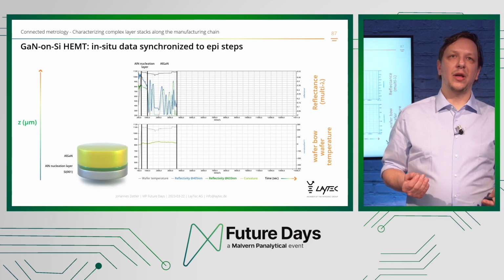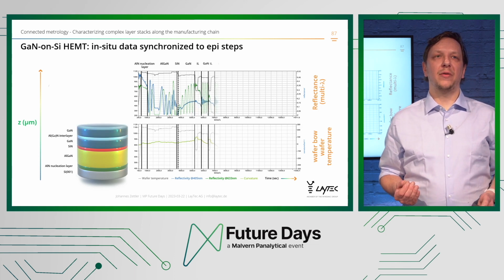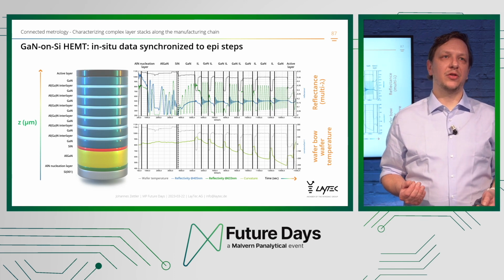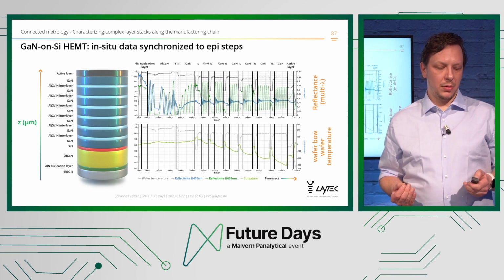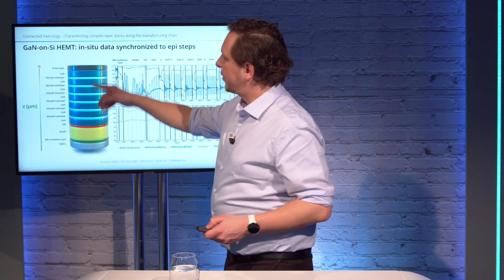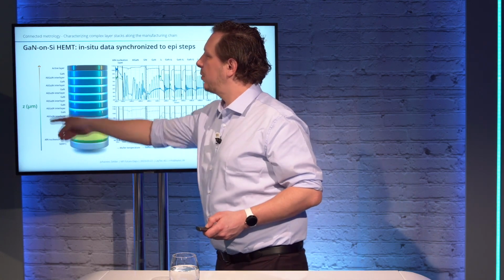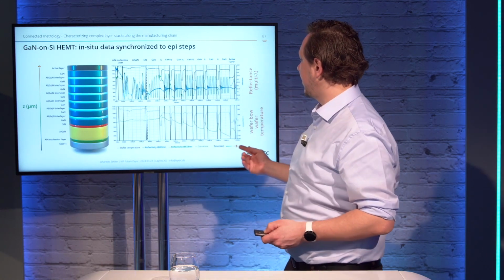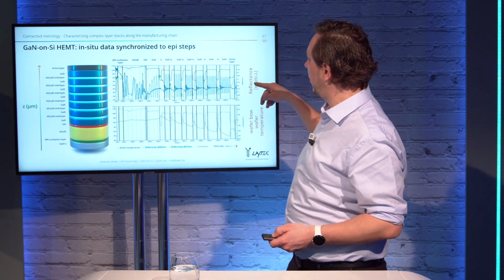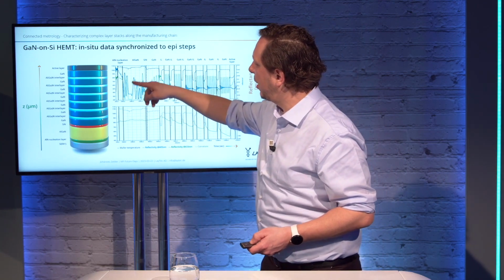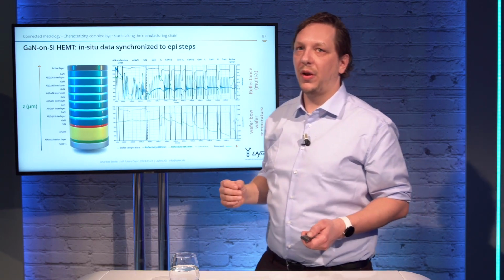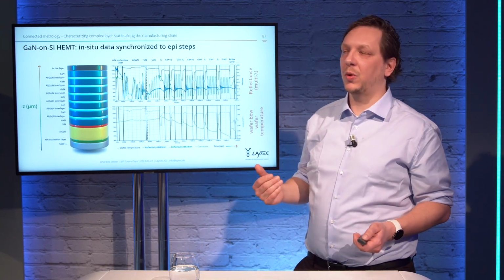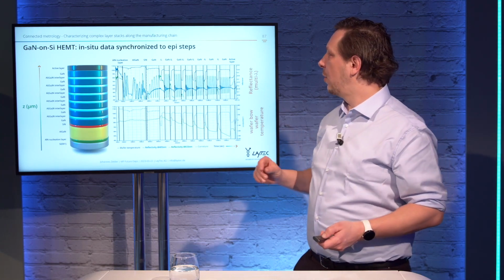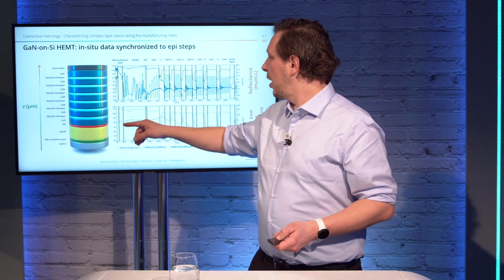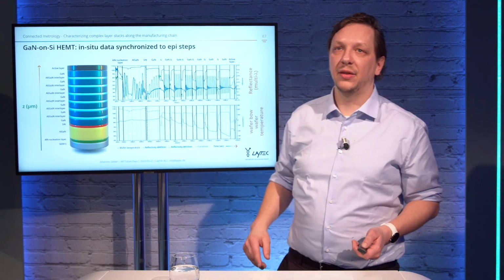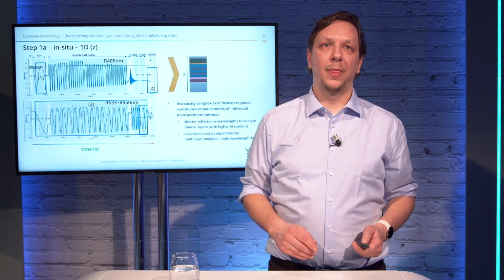So how does the data look that we acquire during measurement? We have here a typical GaN-on-Si HEMT structure, and we see here a schematic of the structure with the growth direction, and at the same time we acquire the data. For reflectance, we see here the reflectance at 2 wavelengths, for example. We see these oscillations, and these oscillations allow us to derive the critical parameters like growth rate, from which we can later on deduce the layer thickness or also the optical properties and composition. And with the curvature measurement that we see down here, we have access to the local strain in our samples.